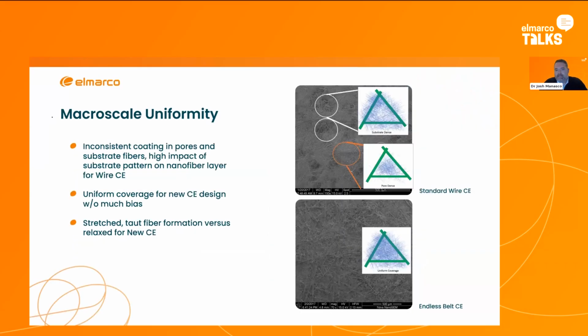And then looking at the macro scale uniformity, you can also see sometimes where there's some hole in the substrate or some bigger gap between fibers of a spun bond, for instance, where you can see that the fibers will sometimes coat lightly in some spots and heavily in others. Sometimes when you're using this belt, you have a nice uniform material behind it, so it really gives you a nice uniform coating, and you can even get higher uniformity in some cases with the belt than you can achieve with the wire electrode, depending on the substrates and the materials that you're spinning.